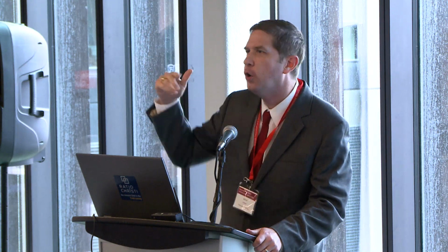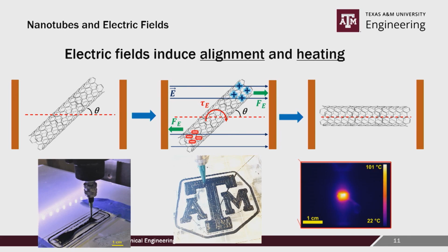So if you have the nanotubes in a thermosetting resin, like epoxy, you actually have a race. Which one will win? Will the nanotube be able to align? Or because it heats, will it cure the polymer around it and lock itself in place? And depending on how you tune that electric field, you can see both behaviors happen. The reason I care about this so much is because of the 3D printing work that we have going on. There are a lot of rheologists who are focused on 3D printing right now. One thing I can tell you is if you're trying to 3D print thermosetting resins, it's kind of a pain.